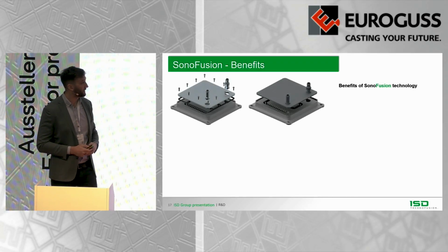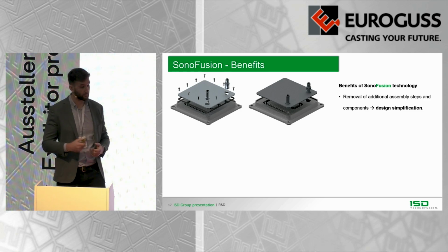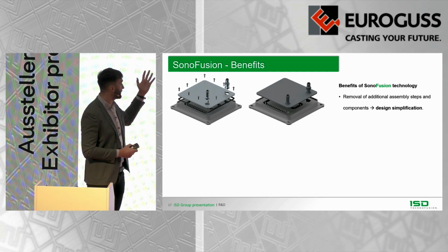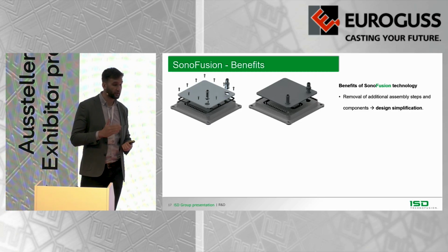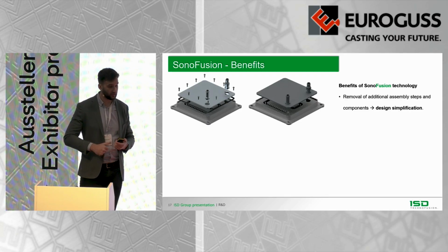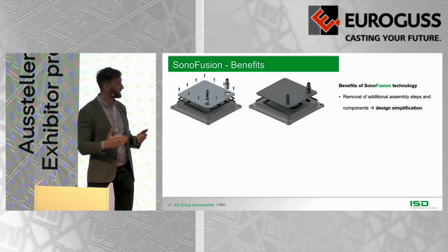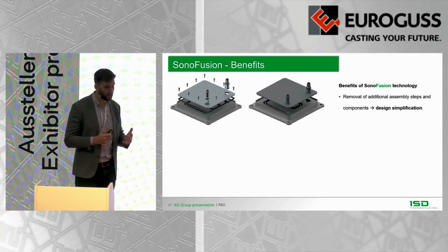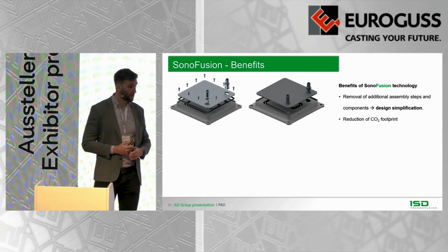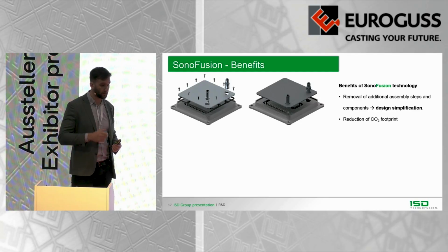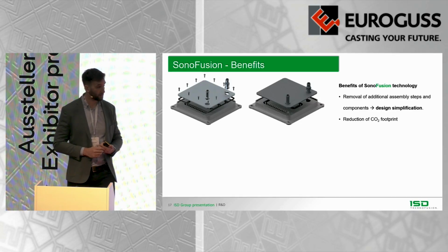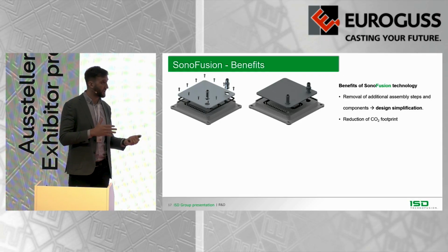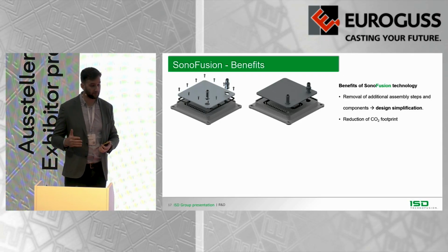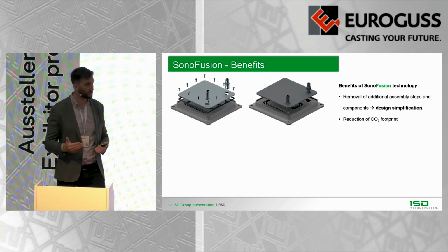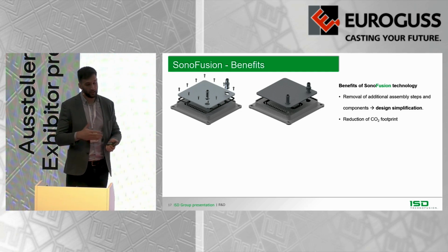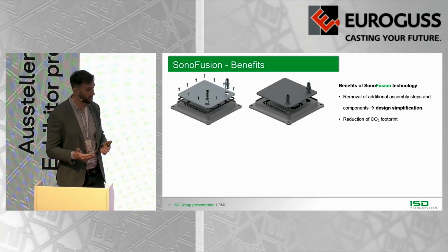So I would say the main benefits of this technology in comparison with others, first of all, if you just compare with standard assembly, you saw that you get rid of a lot of additional components, screws, sealings, and so on. Also, the assembly process flow is much, much shorter. So also a reduction of CO2 footprint because, for example, what many people from casting are not familiar with is that polymers itself, especially technical polymers, are much, much more expensive per kilogram than aluminum alloys. So let's say if a 226 aluminum alloy costs around 2 euros, a technical polymer may cost around 4 to 5, even 6 euros per kilogram.